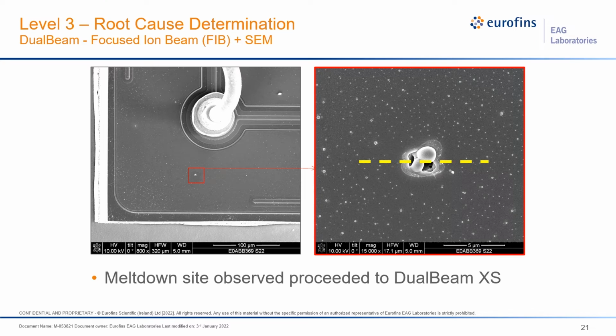Now if we use the SEM, we know where to look on the sample from the OBIRCH. We can then zoom in right here on this location, and we can see that we have a significant meltdown site. It looks like the sample in some ways maybe chipped out, like the sample's broken, and then also evidence of melting and resolidification in this location. And so then we can proceed now to level 3, where we're going to initially start with dual beam cross-sectioning.